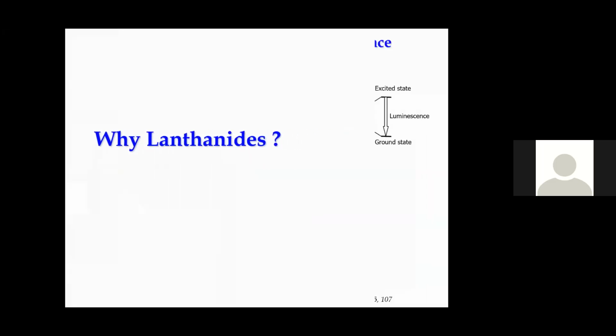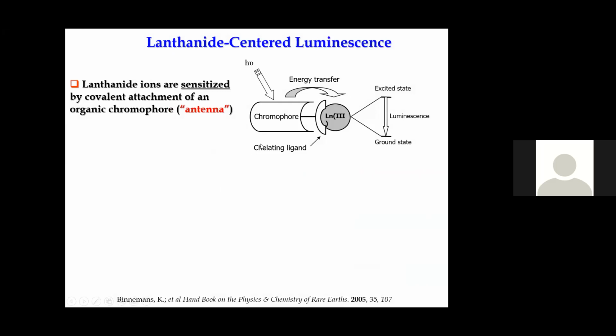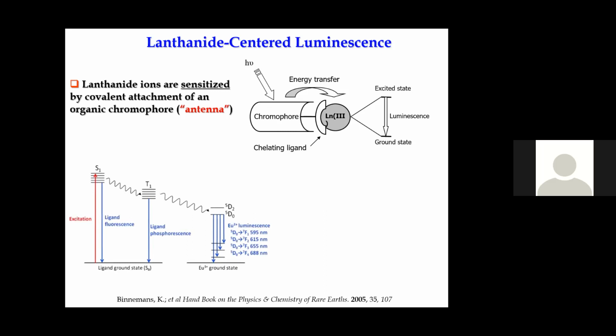So why lanthanides? I'm going to start talking about the photophysical properties here. What we do is we have the lanthanide metal and we attach something called a ligand, or an organic part or a molecule. We call it a sensitizer molecule, which is an antenna. What it does is it absorbs light and it transfers that energy to the metal center so the metal can emit. So this is something called the Förster energy transfer mechanism. The first step is you shine light, so the compound gets excited to the singlet level. And if the electron goes down by releasing energy, we call it fluorescence, but that's not what we want.